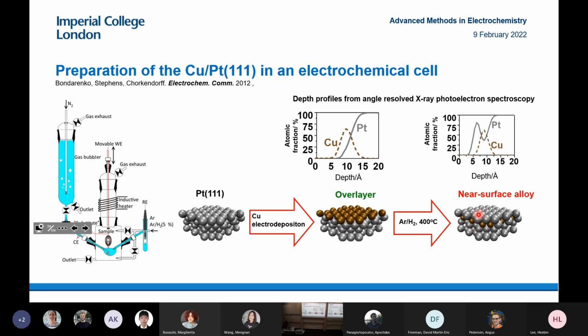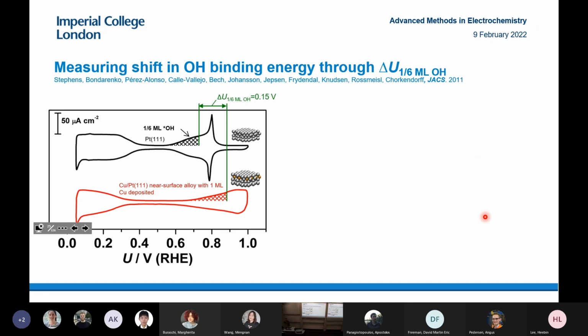We expected that by changing the amount of copper in the second surface layer, we could tailor the reactivity to the reaction intermediates. So when we put the platinum into the electrochemical cell, after depositing one monolayer of copper and then annealing in hydrogen, this is the result. This is pure platinum, and this is the platinum-copper near-surface alloy. What you can see is that you require more positive potential to adsorb OH. And if you had a completely homogeneous surface, the shift in the potential would be equal to the shift in the binding energy of OH, which is the reaction intermediate for oxygen reduction.